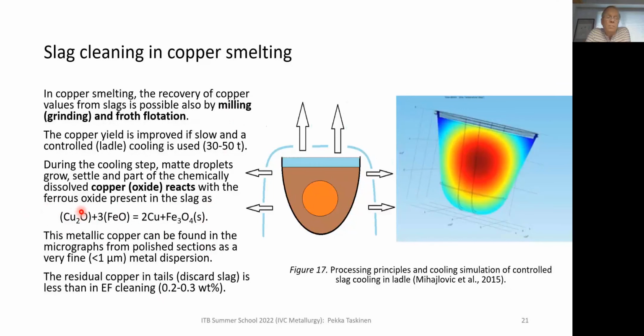from the silicate, and the residual copper in these fine dispersions is actually the kind of residual copper concentration of the discard slag.